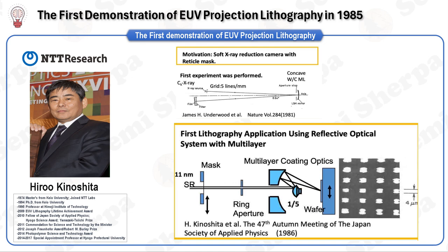He conducted exposure experiments at the Photon Factory in Tsukuba. However, the initial stages of this endeavor were fraught with challenges. The rudimentary visible microscope use led to significant alignment issues, causing the patterns to be severely distorted. But Kinoshita was persistent in his efforts. By 1985, after consistent hard work and adjustments, he achieved the distinct pattern you see here.